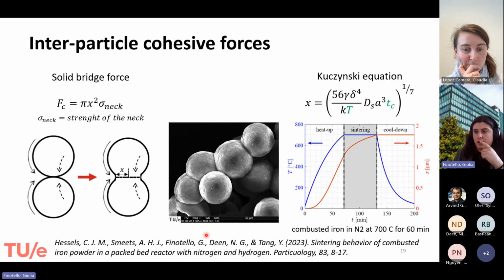So again, my colleague Konrad Esel, during his PhD, did some measurement of these interparticle cohesive forces. So of this solid bridge, which is a formation of this neck over the particle, as you can see represented here by the schematic. So we look into the strength of the cohesive force, which is proportional to the strength of the neck and the length of this bridge. And then what we did, following this equation, these are all properties of the material, and we did measurement at different temperature and at different sintering time or contact time.